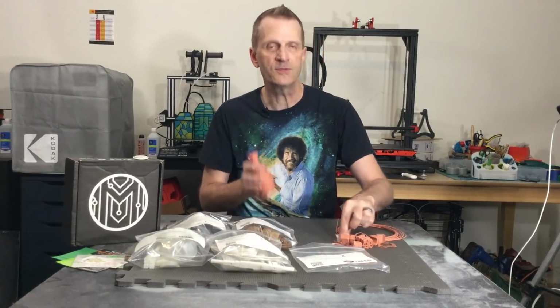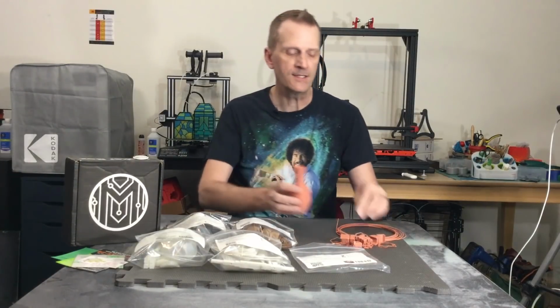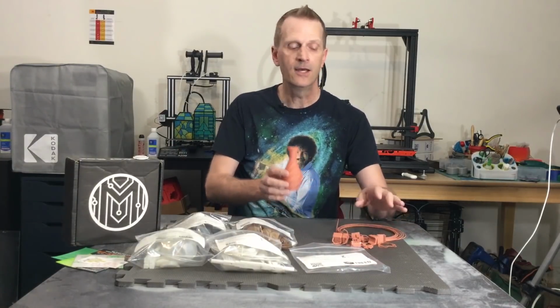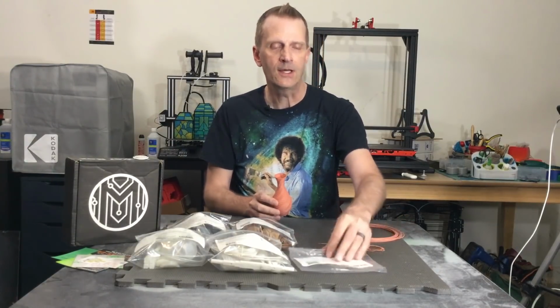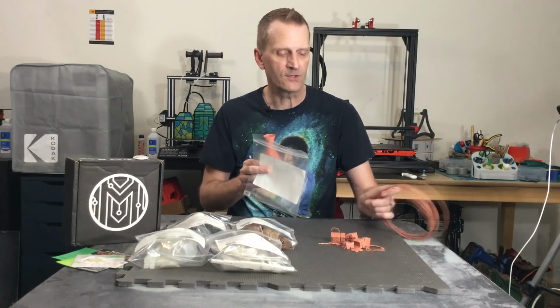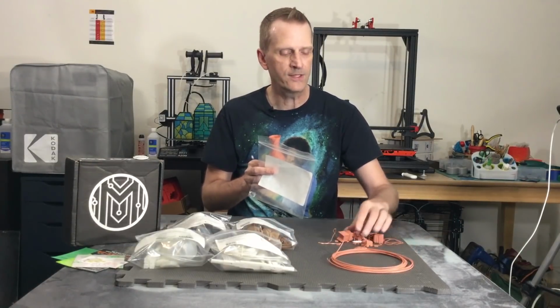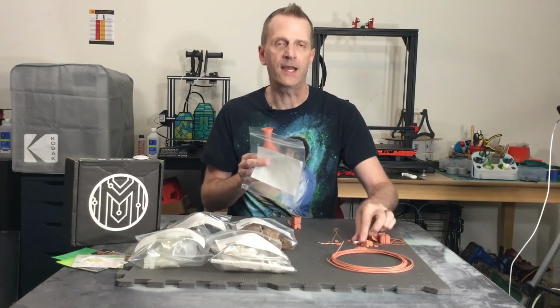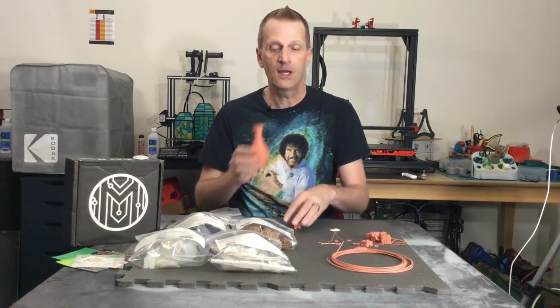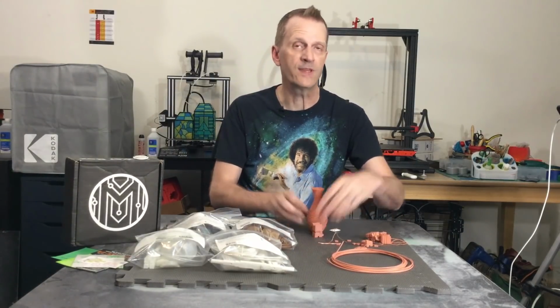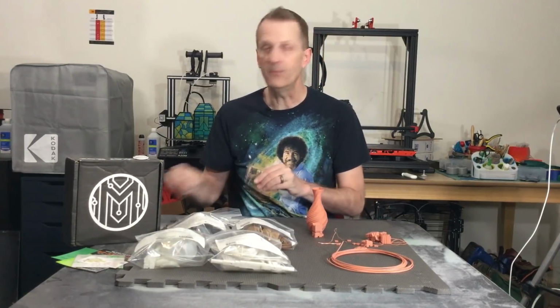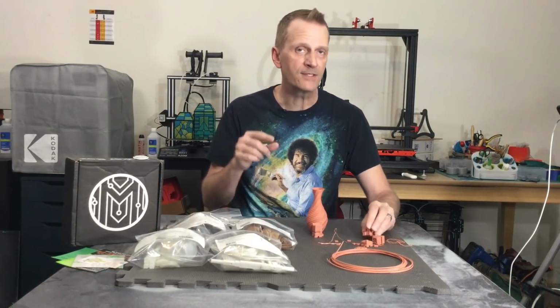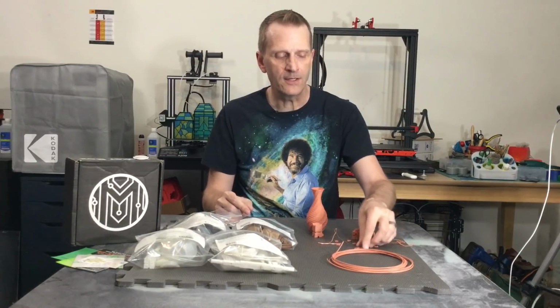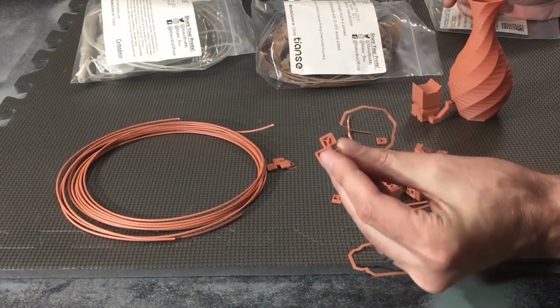The biggest issue I had was bed adhesion. Now, the first thing I did was I removed the heated bed from the G-Max and I put the acrylic back on because I trust the sanded acrylic. I put a lot of faith in that sanded acrylic because it's always done me well. It's always given me successful prints, and I've never had bed adhesion issues until I started testing other kinds of filaments with additives in them. And that's where I saw some bed adhesion issues. But again, I went back to the sanded acrylic. I couldn't get the prints to stay on the bed. They started to warp up.